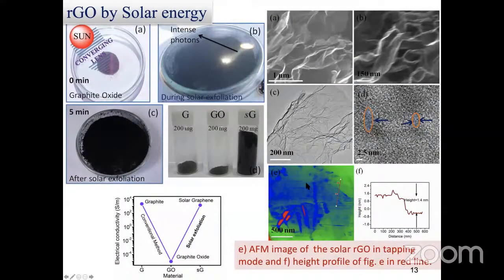Okay. There's also a different, simplest method of making graphene in large quantities. What you can do is make the graphite oxide. In the previous slide, I've shown that after graphite interacts with the oxidizing agent and acid, one can get this graphite oxide that can be easily exfoliated with the sun's energy. Just use a converging lens, and in no time one can do the solar exfoliation. So this is called solar exfoliation.